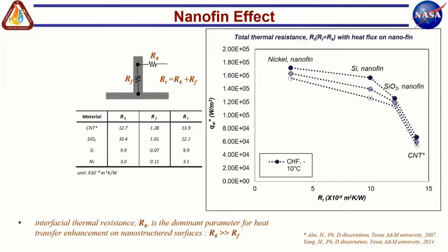And part of the reason, I think, is we are estimating the total resistance wrong. I wouldn't say wrong, but we are probably making a big error on the estimation of the total resistance using molecular dynamics simulations. Part of the reason is molecular dynamics simulations cannot account for the electron gas that occurs in metal crystal structures. And so that interaction between the electrons in a metal lattice with the coolant is something that we are not capturing right now. And so therefore, I think we are probably over predicting the resistance when it comes to nickel and carbon nanotubes.